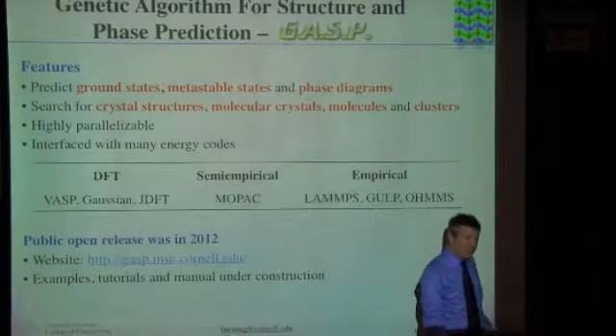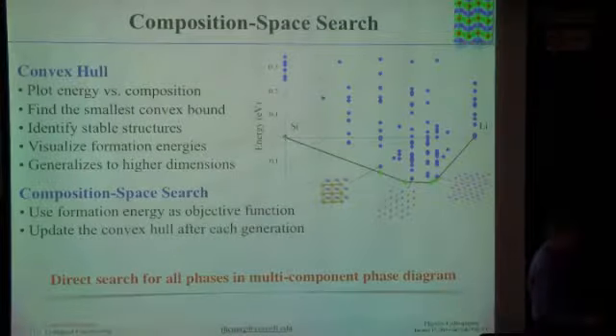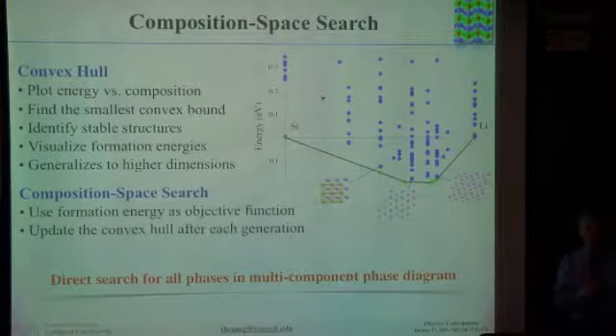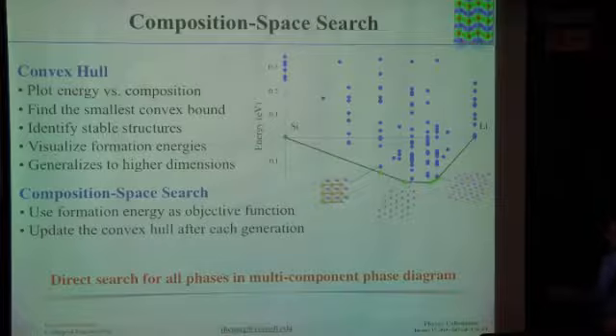So one thing which is unique about our work is that we do a composition search. You don't have to tell us what composition you're interested in. We're going to find out at which compositions the structures actually occur. And while I say that, I should also give you one little caveat about all these structure search methods. We limit ourselves to somewhat small unit cell structures. That's an input parameter, and for most calculations, we set it to something like 20. Twenty-atom unit cells are quite efficient. Anything much larger than that gets somewhat slow. You can probably go up to 40 if you look at a small composition range, but beyond that it gets hard.